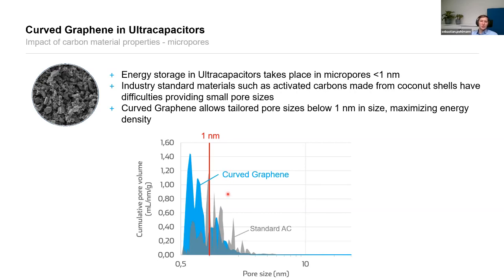But what we managed to do with curved graphene is to get basically one peak here. It is a little bit split, but it is basically one big peak of very well defined pore sizes. That normally brings you increased capacitance, and we have the proof of that in an industrial large cell: instead of 3,200 farads, we get 5,000 farads when we use the same amount of curved graphene compared to activated carbon. So that is what we actually do in terms of material research, and what to consider when you work on it.